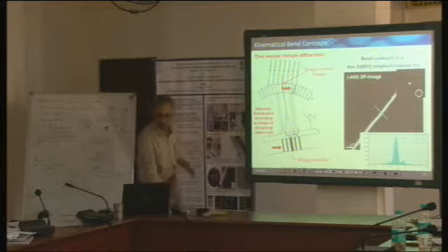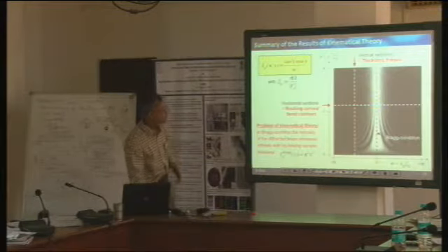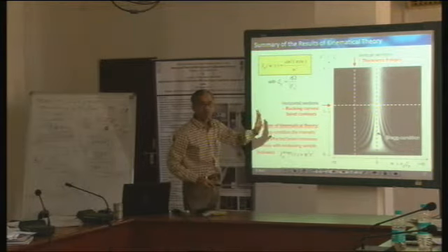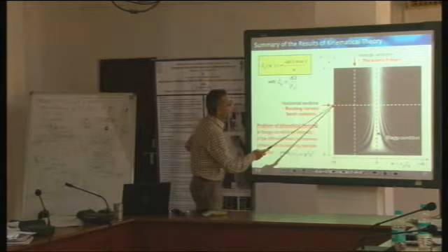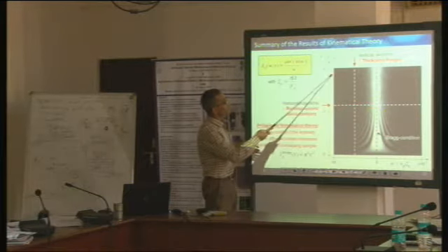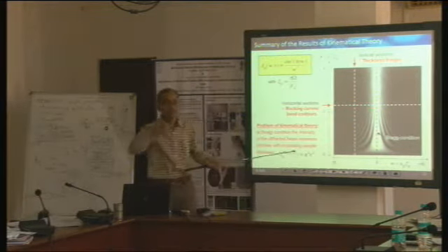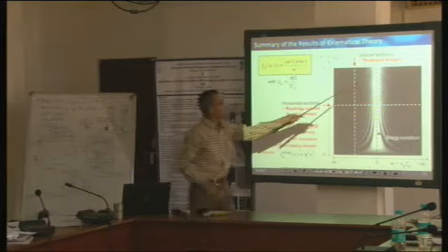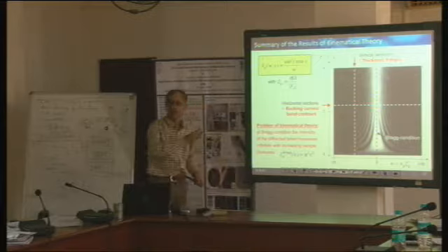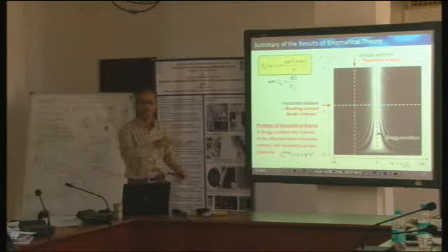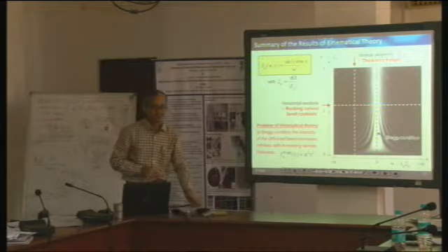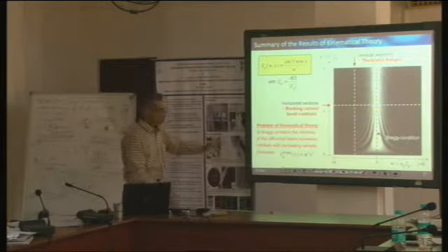Here it will not, because if you look at this plot, it says that irrespective of any thickness, I have drawn this curve. Even if I draw it here, the pattern is likely to be similar: maximum intensity at the Bragg diffraction condition, and as you go away from it, the intensity decreases, but also shows side fringes. But this is not really so.